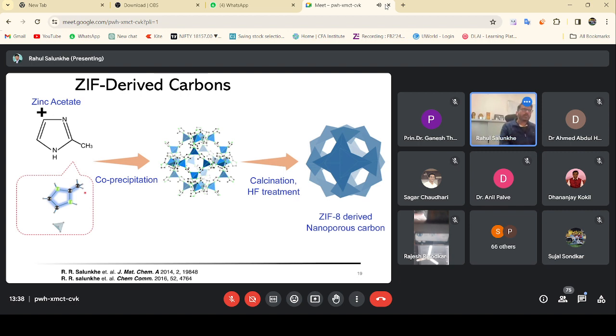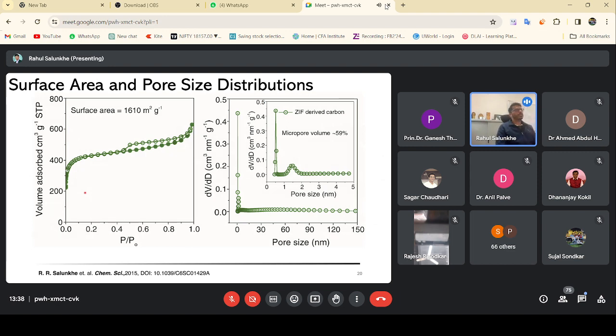This is a very simple synthesis, and because of that we got a typical surface area. BET shows MOF-derived carbon has a very highly stable porous structure and high surface area, which can be changed depending upon the synthetic condition, what kind of heating temperature you use. Depending upon that, the porous structure can change. ZIF-8 derived carbon has shown a very stable porous structure with a surface area of around 1610 square meters per gram. This is very essential for any supercapacitor application.